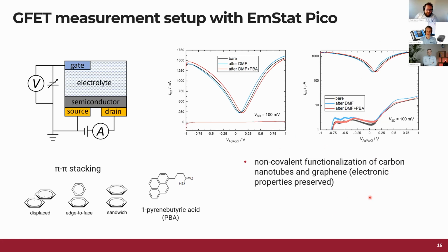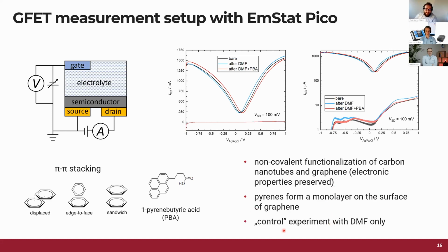So to sum up this slide, the non-covalent functionalization of carbon nanotubes and graphene is possible with those pyrenes, which preserves their electronic properties, and pyrenes form somewhat a monolayer. There's still a debate on how exactly they interact. There's a couple of papers on that. And then what I would like to point out and underline: always make control measurements, because you can end up having a situation like this in here, that the solvent itself changes the surface of a clean bare device, and not only the pyrene, not only the active ingredient in the mix.